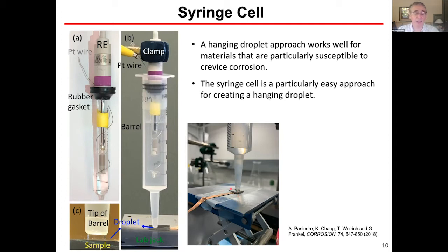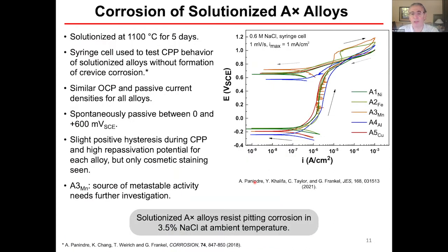In fact, the approach is very similar to some microcell approaches, except the intent is not to have a microcell area, although the area will vary with the size of the syringe. You can use large syringes and have relatively large areas, but the droplet eliminates the crevice. And it works quite well. Here you see these alloys. These are now solutionized, but in this syringe cell, we can see that there is really no crevice that formed.